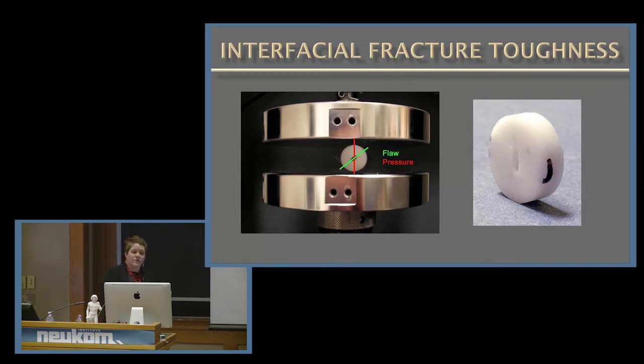We looked at thermoplastic adhesives, which are adhesives that set by solvent evaporation. And these are our nice reversible adhesives. One we're going to talk about is B72, an acrylic adhesive. And then thermosetting, these are just broad categories of adhesives. Thermosetting adhesives are really what we know as epoxy. They cure by chemical reaction. And they're very, very, very strong. In fact, maybe far too strong for something like the sculpture. Which is good, but they're quite difficult to reverse. So we're trying to avoid using them in conservation as much as possible.